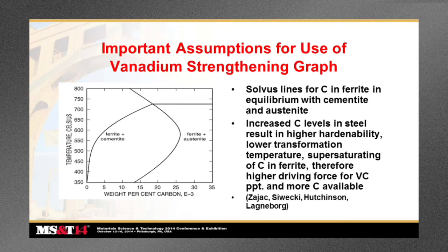It's work done by Zajac, Siwecki, Hutchinson and Lagneborg, that proposed that at intermediate carbon levels in the 0.20 carbon range, during cooling through transformation, you can, in fact, get a supersaturation of carbon in the ferrite. And that's represented by this solvus line that shows the equilibrium between carbon in ferrite and austenite to the right, versus in this case, where you in fact reach higher carbon levels in the ferrite than you would if you simply have an equilibrium between the ferrite and cementite that normally forms during the transformation of austenite to ferrite.